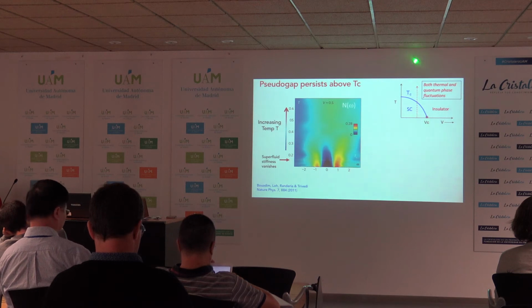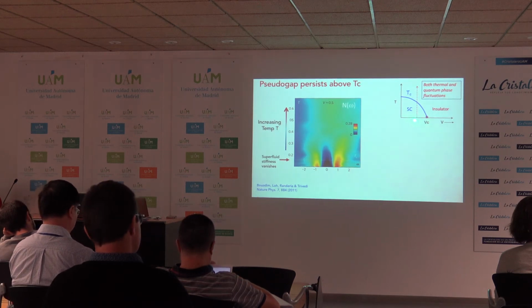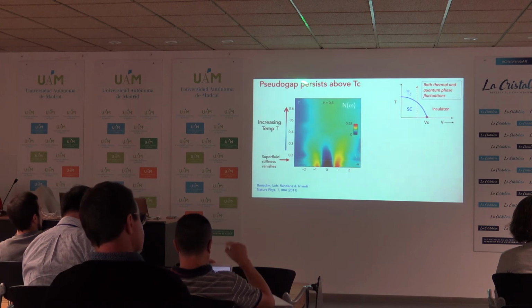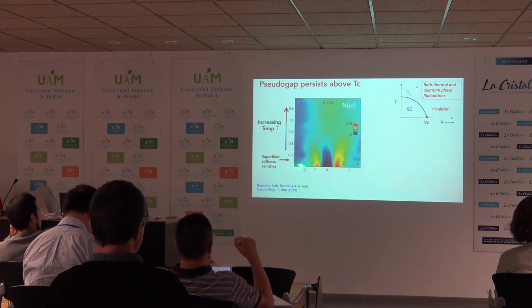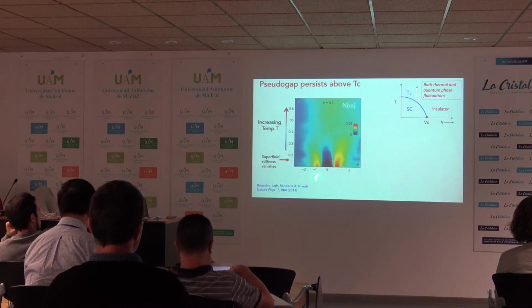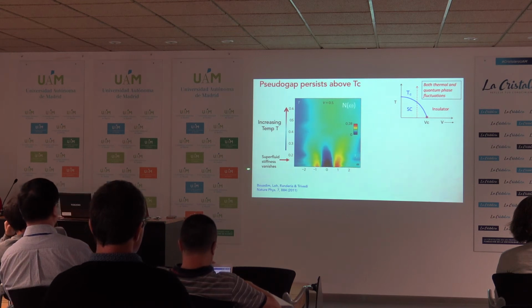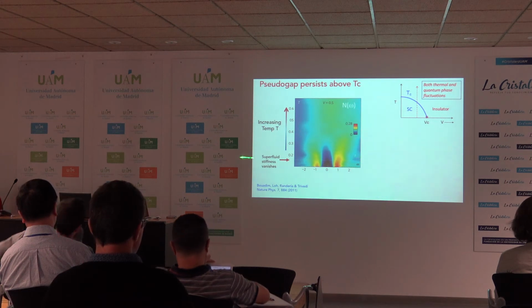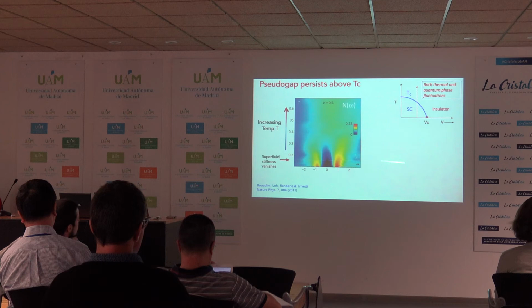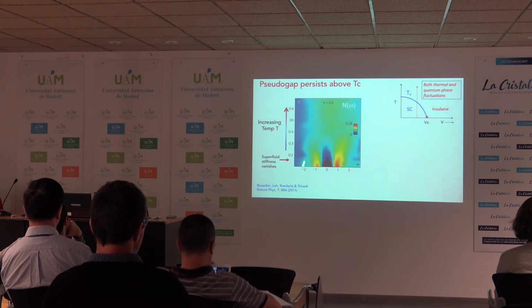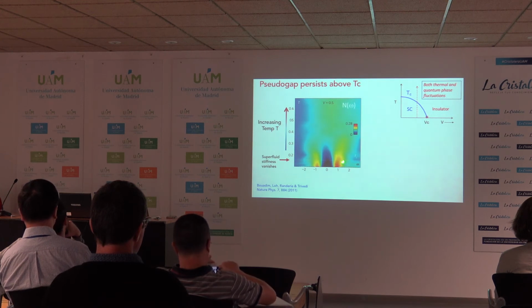Now we can also take a cut like this and fix the disorder on the superconducting side, but increase the temperature. And now you see that this is again this single particle dI/dV as a function of omega. You see the hard gap starts to fill up, and again this is where rho s vanishes at the transition. This is the Kosterlitz-Thouless transition with a jump. This is the finite temperature transition. But you see even beyond that, a pseudogap persists at finite temperatures.